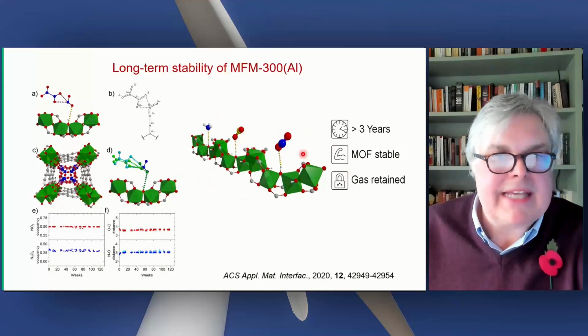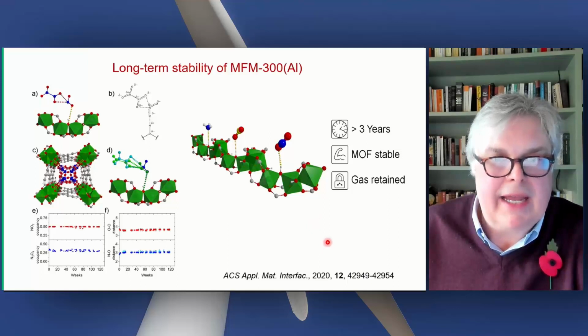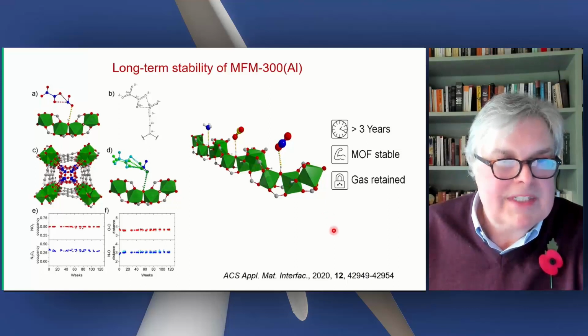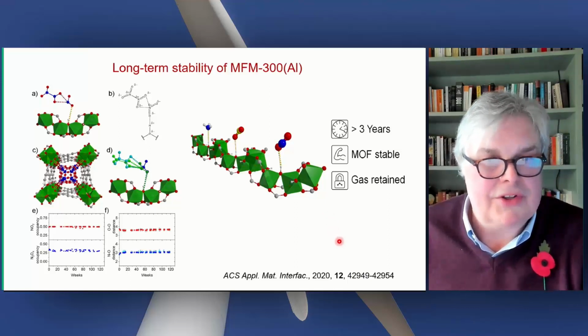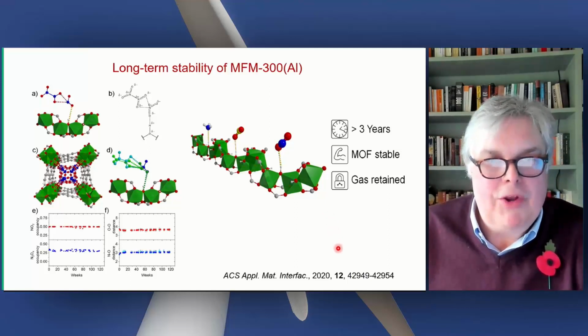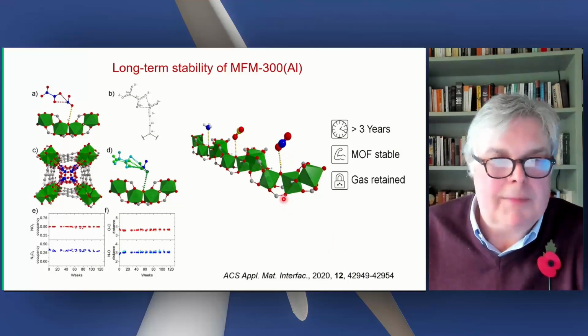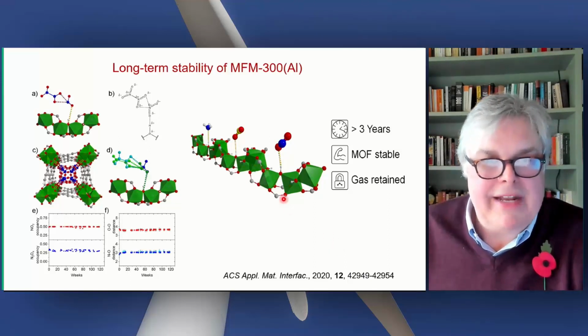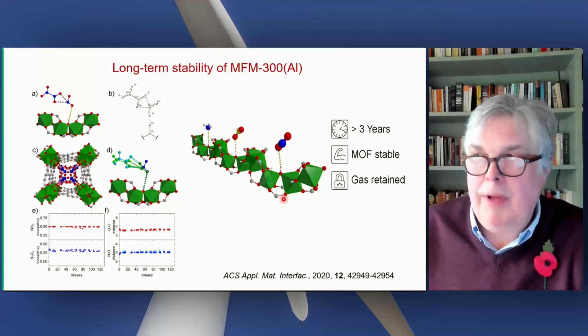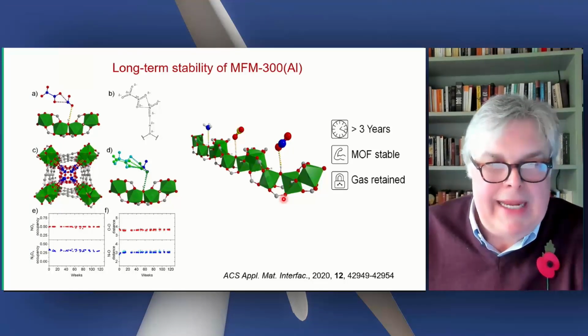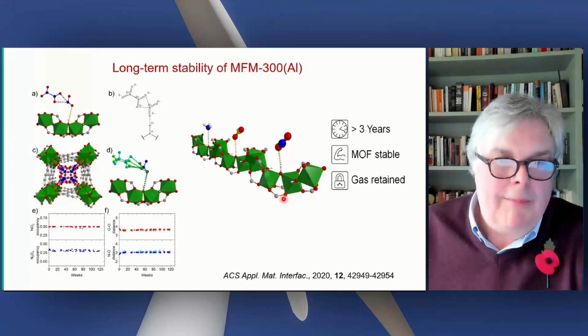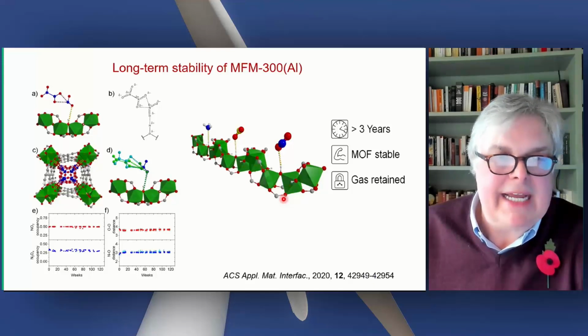And we can make this aluminium MOF, as I say, in kilogram quantities to scale in very high purity. This, of course, is something else as a synthetic chemist I should emphasize. Some of these syntheses are not straightforward. You, of course, are forming insoluble products. Often they're carried out hydrothermally in a bomb. You heat the bomb up, and the reaction runs for between a day and 2 or 3 days.